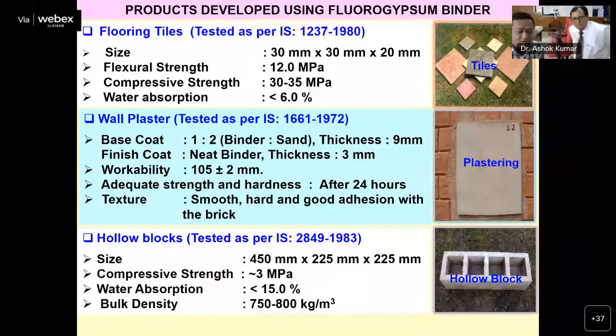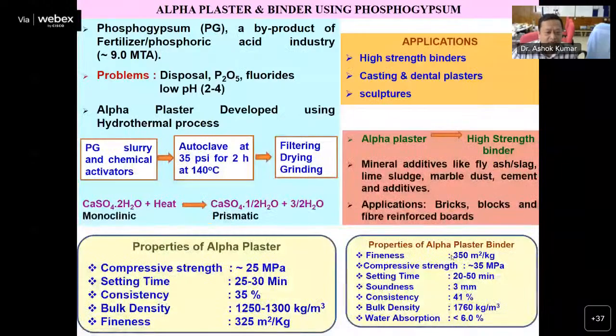Thank you, sir. We were discussing the alpha plaster, which has been developed using the phosphogypsum, a phosphoric acid industrial waste. This alpha plaster is developed first by autoclaving, heating it at 140 degrees centigrade. It is a hydrothermal process. This alpha plaster has very good compressive strength, more than 25 MPa, and low consistency. It can be used for high strength binders, casting and dental plasters and sculptures.